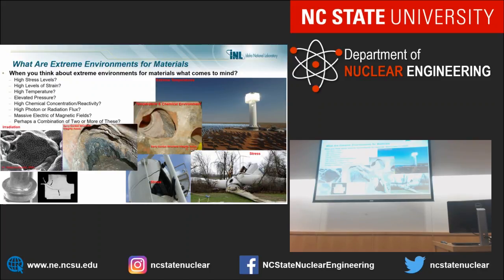And on the cladding, some of the cracks on the cladding were 75% through wall. So the only thing that stood between us and a catastrophic accident in Davis-Besse was 25% of 1/4 inch. So about 1.5 millimeters, okay? That is fuel, gases, radiation, caused that really nice pattern. While it looks nice for all sorts of designs, not good for energy.